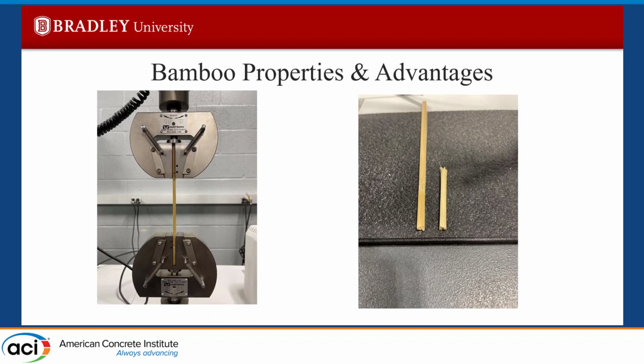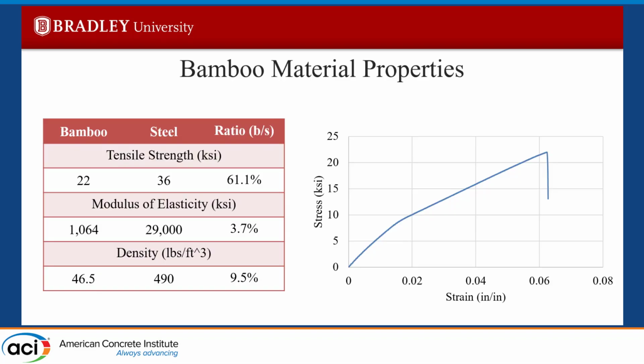And then this is just the test setup of testing the tensile strength of the bamboo. As you can see in the far right picture, it has a brittle failure, unlike steel, which kind of bends. And then here are more bamboo properties we're going to talk about. On the right, we have a stress versus strain graph. As you can see, it reaches a kind of linear line up to 22 KSI, where it then falls straight down, which means it has a brittle failure, which was expected. And on the left, you'll see our table where bamboo has an overall tensile strength of 22 KSI, which can be seen in the graph, a modulus of elasticity of 1064 KSI, and an overall density around 46.5 pounds per foot cubed.